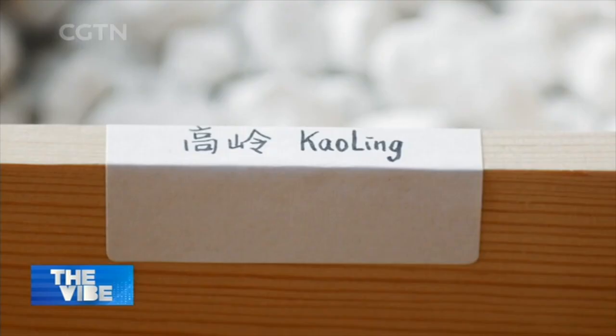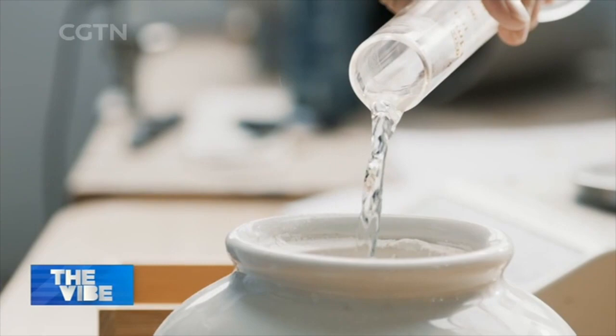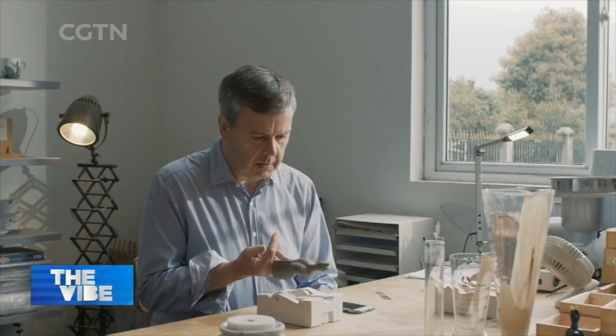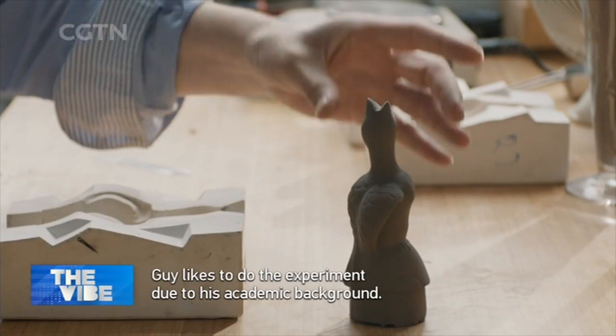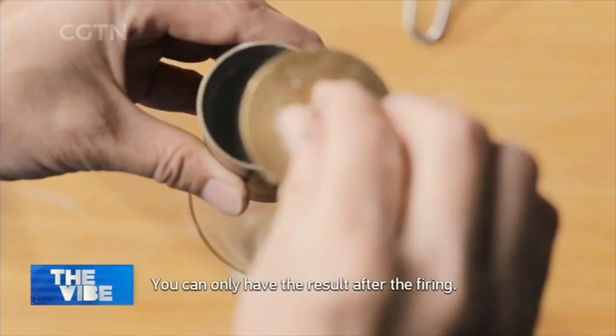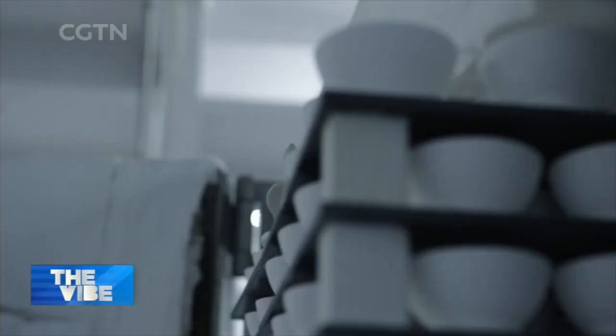What they found in one shop was a supplier who could tell them the vague percentages of the three main ingredients — kaolin clay, feldspar, and porcelain stone. It became Guy's job to research the ingredients. A duckling model was chosen for Guy's experiments, bearing the responsibility of confirming whether each formula was sound. These ducklings look exactly the same but are grouted with different formulas. Guy fires them in a gas kiln at a stable temperature.